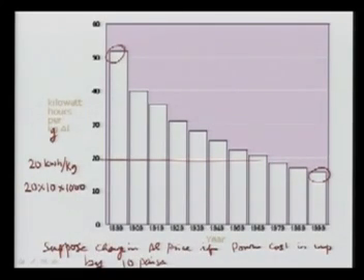So you multiply this and divide by 100 because you want to get the rupees, and then you have 2000 rupees per ton of aluminium. I think we did it correctly. So just get a feel: if the rise in the cost of electricity is 10 paisa per unit, that may result in the cost of aluminium going up by about 2000 rupees per ton. That's a very, very significant amount.